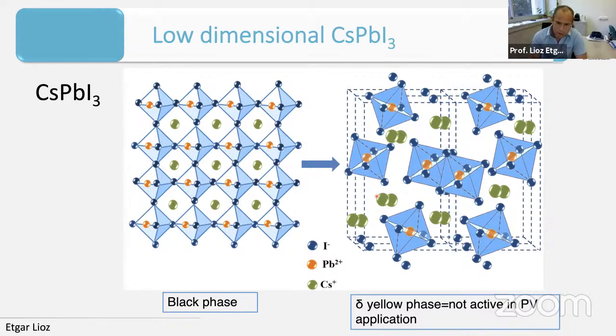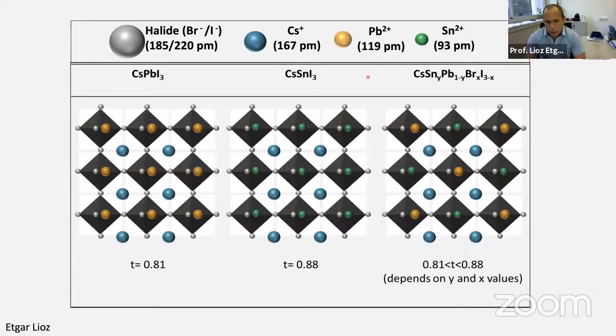And there are several ways to try and stabilize this structure. We thought of a way to create an alloy structure, which means that we can create some mixing of lead and tin at the metal site, as you can see here. If you look at the size of the cations, they are not the same size, which, as you will see in a minute, creates some tension in the crystal. But on the other hand, this tin should stabilize it. Instead of the cesium lead iodide completely going to the orthorhombic phase, which is unstable and non-active, maybe this addition of tin will make some stabilization to the structure.